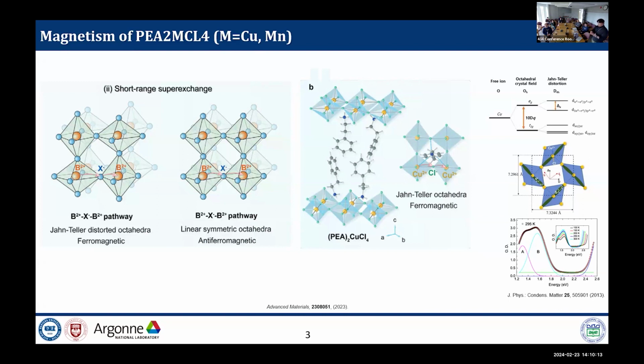This ordered state of copper near the chlorine and another copper has a superexchange interaction. So this makes in-plane ferromagnetic ordering, right? This is a Jahn-Teller distorted octahedral ferromagnet.